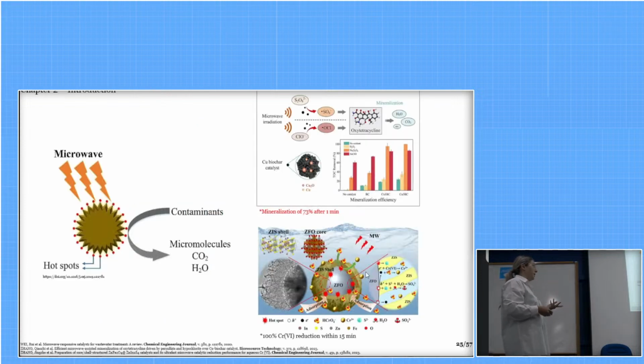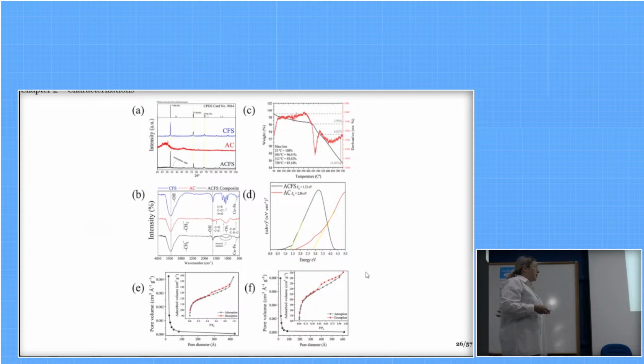So, knowing that microwave can interact with carbon sources to form hotspots and degrade contaminants and micromolecules, we observed that in the literature, some results were already showing high mineralization rates within 1 minute for oxytetracycline, and the possibility of reduction reactions under microwave assistance. So we produced the heterostructure, and here through XRD we confirmed the stability by the addition of the amorphous structure to the crystalline peaks. The same patterns for the